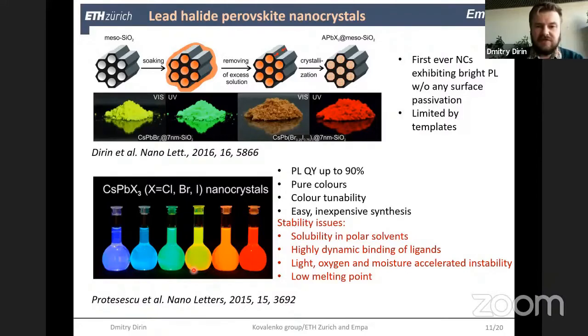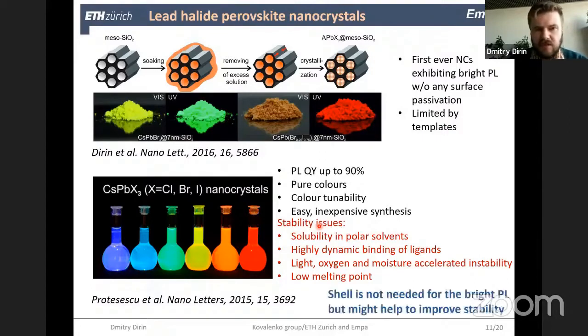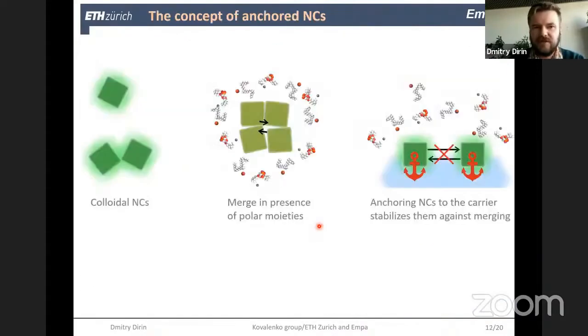This study has already shown us that indeed those materials can be bright even in the presence of surface states and even in the presence of dangling bonds. This explains why we don't really need a shell around those materials to make them brightly emitting. But a shell could still help to make those materials more stable, because, as I mentioned a moment ago, those materials are very sensitive to moisture, and a shell could protect them from the moisture. But those materials are very ionic, and it's very difficult to grow a shell around them. It turns out to be much more difficult than in the case of conventional semiconductors.